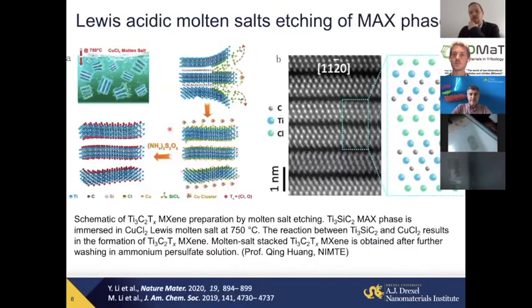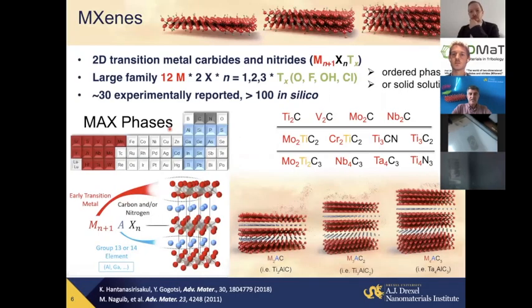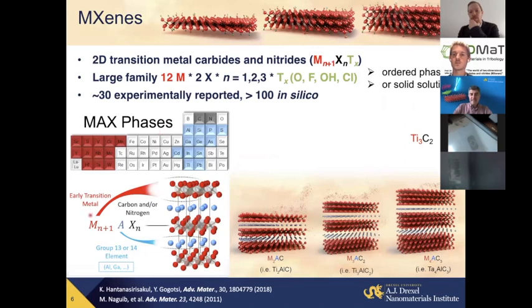A rule of thumb, I would say, is that thinner MXenes are less stable compared to thicker MXenes. So say niobium 4C3 will be more stable than niobium 2C. Titanium 3C2 will be more stable than titanium 2C thermally. But also defects, surface terminations, and flake size contribute to their stability.